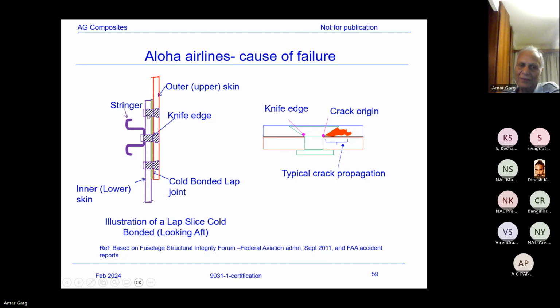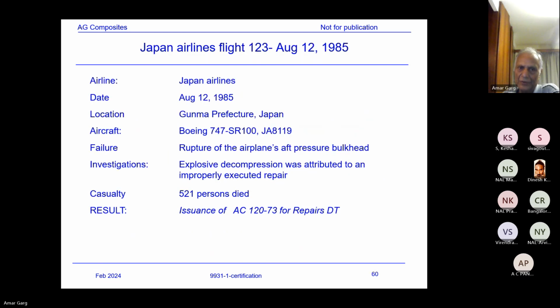And during maintenance, the cracks which were generated, a sequence of cracks, were also not detected. And then gradually the fatigue cracks were initiated, propagated, and caused a sudden failure. Anyway, so that was the history of that.